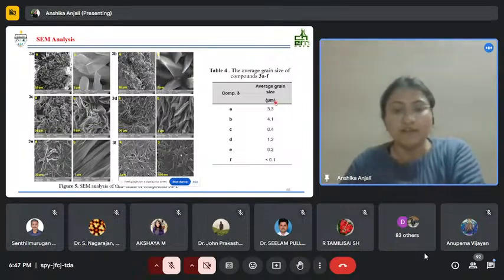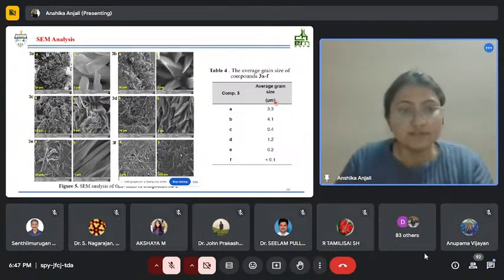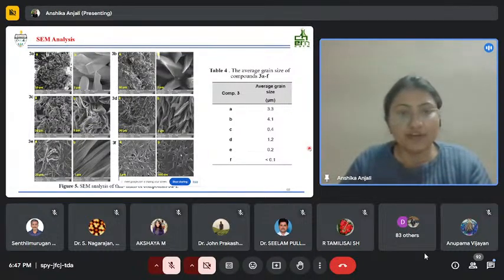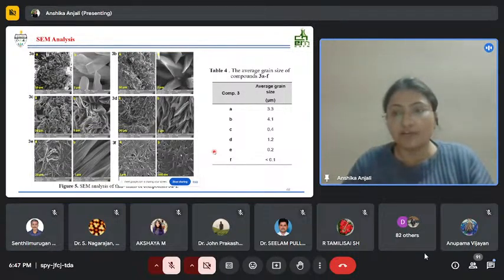The fabricated active layer morphology was determined using the scanning electron microscope technique. Here, with different functionality, we have versatile morphology. From there we have calculated their average grain size values as well. When we look at it, we can see there is uniform coverage, which will facilitate their mobility values.